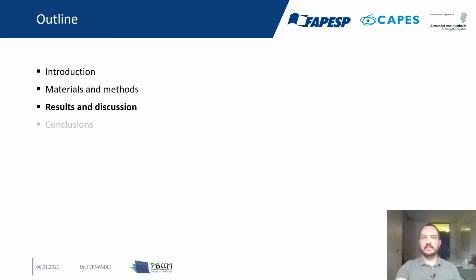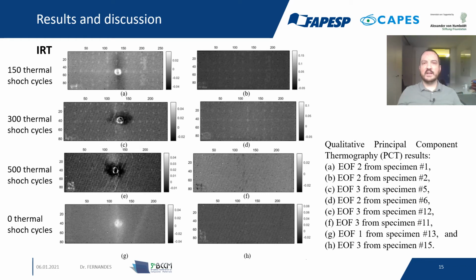Now our results. Infrared thermography signals are very subtle. Thus, one must apply enhanced signal processing techniques in order to have a better defect visualization. Here in our work, we apply principal component thermography, a well-known method that has been used for more than 15 years now, which relies on singular value decomposition in order to sort components, putting the most valuable and relevant information in the first components of the result. Thus, we can reduce the amount of data from 1,000 thermograms, for example, to 10 components that are really relevant.